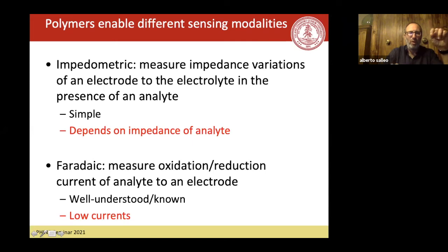In principle, measuring impedance is very simple. You send a sinusoidal wave, a little voltage, and then you measure the current that comes out. The problem, though, is that this depends on the impedance of the analyte as well. This is a mistake. I should say depends on the impedance of the electrolyte. So you need to have a reference device next to it, and it's not very selective for that reason.